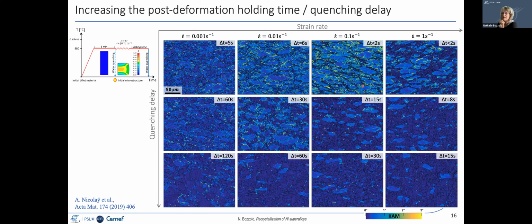Even at the lab scale, if you go for example, 1 per second experiment, you see that the full recrystallization time is something like maybe 20 seconds. And so even if you have a quenching delay, which is as short as 2 seconds, actually here you already have quite a significant amount of grains which are due to post-dynamic recrystallization and not dynamic recrystallization. That's it. All right. So these phenomena in terms of mechanisms are quite simple.